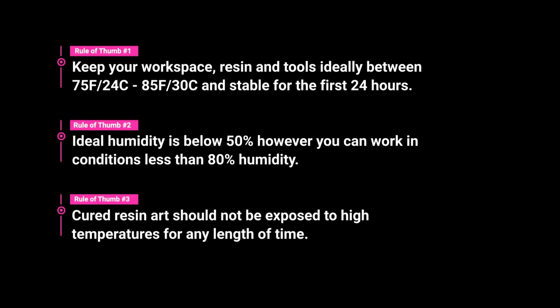So remember, for flawless results during the summer months, always use ArtResin as directed, and remember these rules of thumb. Keep your workspace, resin, and tools ideally between 75 to 85 degrees Fahrenheit or 24 to 30 degrees Celsius and stable for the first 24 hours. Ideal humidity is below 50%, however, you can work in conditions less than 80% humidity. Cured resin art should not be exposed to high temperatures for any length of time. And if you're working with resin in winter, check out our video, How Does Cold Weather Affect Resin?, which has lots of great advice for using ArtResin in winter.